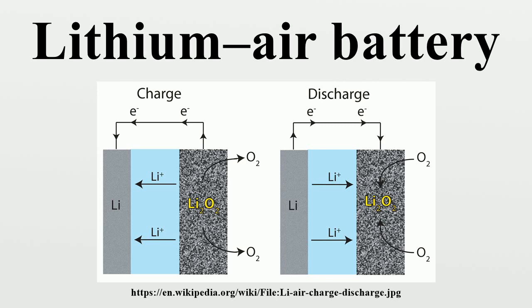Li-ion conducting glass or glass ceramic materials are readily reduced by lithium metal, and therefore a thin film of a stable lithium conducting material, such as Li3P or Li3N, can be inserted between the ceramic and metal. This ceramic-based SEI inhibits the formation of dendrites and protects the lithium metal from atmospheric contamination.